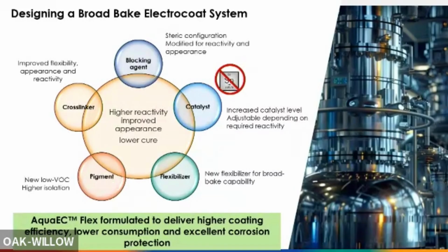Increasing the wet film resistance, what does that do? In layman's talk, during the deposition process, under the influence of electricity, the coating is going to migrate to the part, right? Right at the part, hydroxyls are being released, and we call that the hydroxy boundary layer. During the deposition process, when the coating gets to this hydroxy boundary layer, it coagulates out and becomes a permanent film, right? And it's not reversible. If I can get that coating to coagulate quicker, that gives me more time for the paint to travel to some of these harder to reach recessed areas and coat those as well. So the rate of deposition changes, the coagulation properties change, and the throwpower changes as well, all of which helps us get to the endpoint quicker on the exterior and gives us more time to work to the interior.